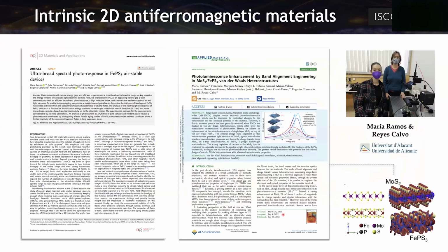Here are some of the works that we have been doing in collaboration also with the group of Maria Ramos and Reyes Calvo in Alicante. We were determining Hubbard-U from the calculations, so from the experiments they have for the semiconducting gap, and this was around 1.9, 2.2 electron volts, and also testing the effect of charge transfer when we create van der Waals heterostructures, that in this case was increasing the luminescence of the molybdenum sulfide. So this possibility always to combine different materials, and with having initial calculations, we can predict what is happening.